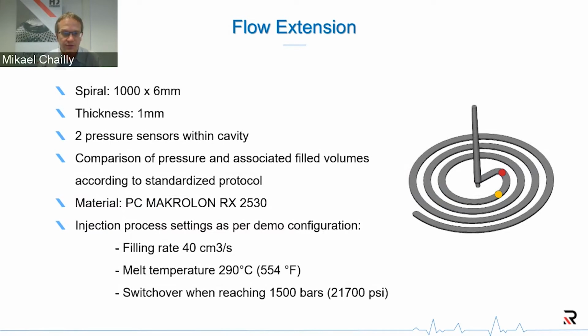For the injection process settings, we used exactly the same as you will see in the live demo: a filling rate of 40 cubic centimeters per second, and a melt temperature of 290 degrees C. We fill until the injection pressure reaches 1,500 bars, and then we switch to a pressure-controlled filling for an additional 3 seconds.